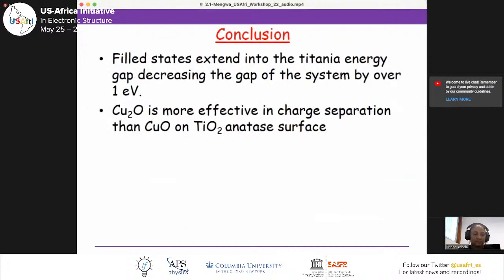We also observe that filled states extend into the titania energy gap, reducing the gap of the system by over 1 electron volt, and therefore shifting its absorption to the visible region. Again, we can see from what we've just discussed that Cu2O is more effective in charge separation than CuO on TiO2.